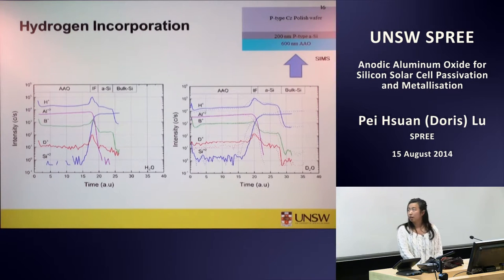So we started to research how much hydrogen content is within the anodic aluminium oxide. This is a SIMS measurement, which is very similar to what the literature has shown. There is a high concentration of hydrogen ions stored within the AAO layer. And it's interesting to see that if we anodize a layer of aluminium in deuterated electrolyte, there is deuterium detected in the AAO layer, which suggests the hydrogen source actually is from the electrolyte solution during the anodization.